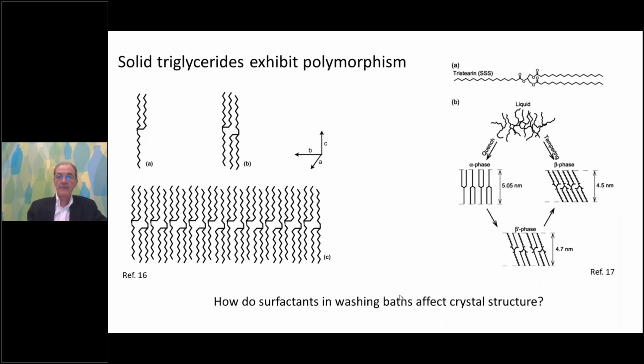And so if you're not familiar, fats or triglycerides like tristearin are triacyl esters, and they're rather bulky. So in the crystalline solid state, they can pack together on the left in this type of form. The 1-2 acyl chains can be parallel, and then the third acyl chain points in the other direction. They sort of form this chair-like shape, and they stack up in the crystals to form this type of crystal structure. Or you can have the 1-3 acyl chains parallel and the 2 acyl chain pointing the other way, and they adopt sort of a tuning fork type of structure, again in the crystalline state.